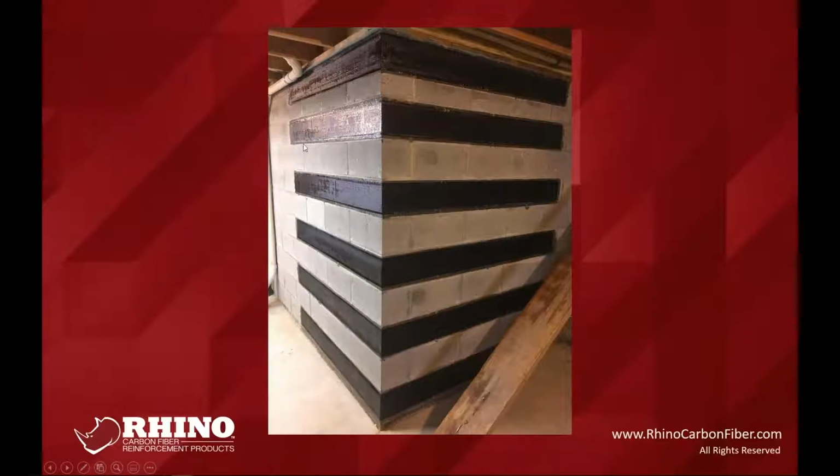So we use a thing called Gorilla Tape. You put Gorilla Tape underneath there. Then when you put the epoxy on and put the carbon in, you can clean it off the Gorilla Tape very well. It doesn't leave marks or mar the wall. Then as the epoxy starts to tack, you can take the Gorilla Tape off. It's no longer running. And you have these pretty carbon fiber installs.